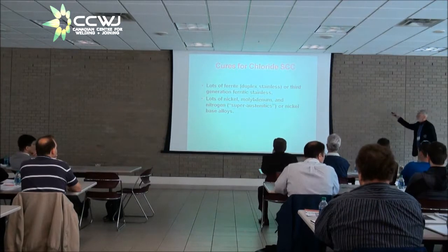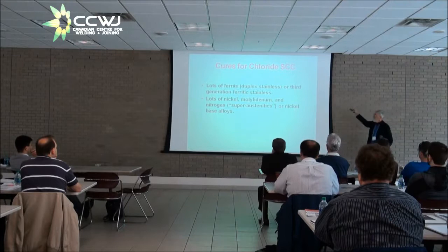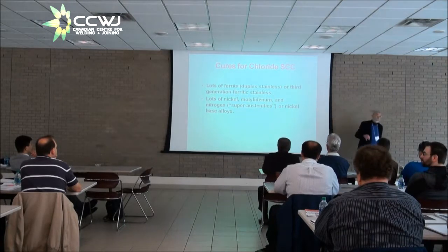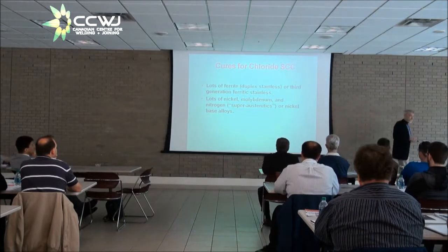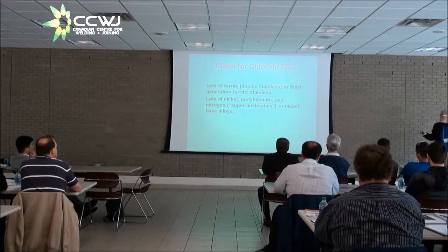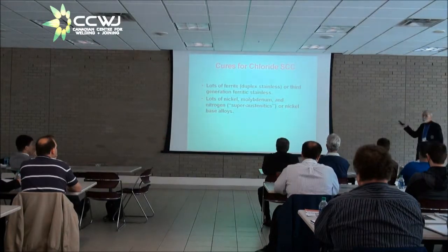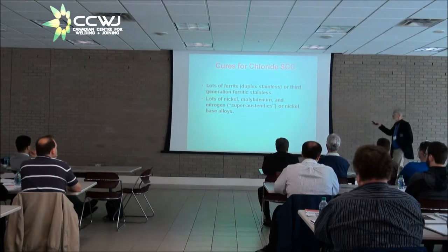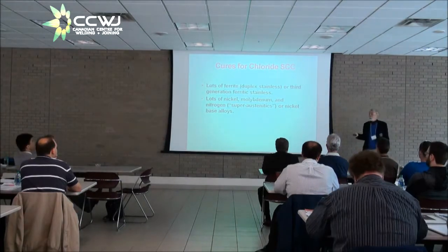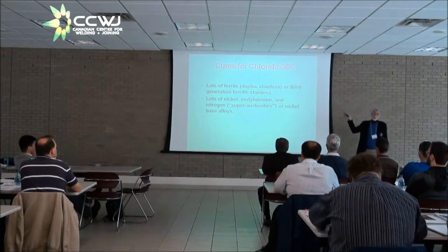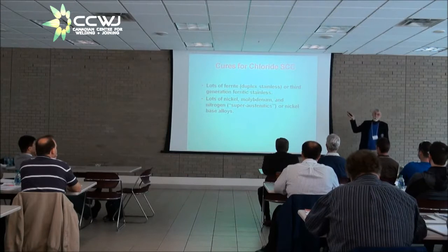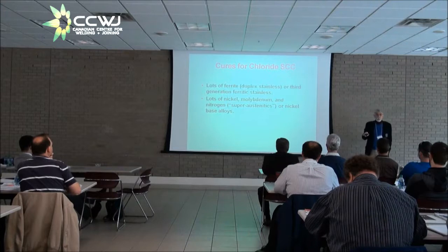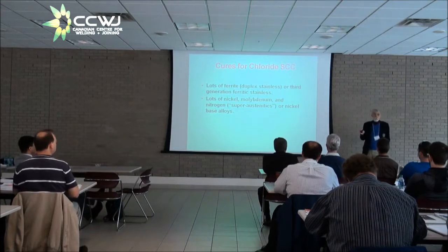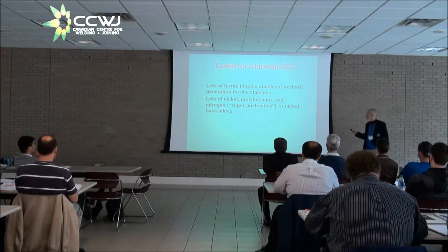The other alternative was to go with lots of nickel, get away from compositions that were susceptible. And that takes you into nickel-based alloys or the so-called superaustenitic stainless steels. 25 nickel, 20 chrome kind of alloys or something like that. Duplex turns out to be the cheapest alternative and the most friendly because you get fabrication properties that are like austenitic stainless steels. In particular, grain growth doesn't hurt as it does with ferritic stainless steels.